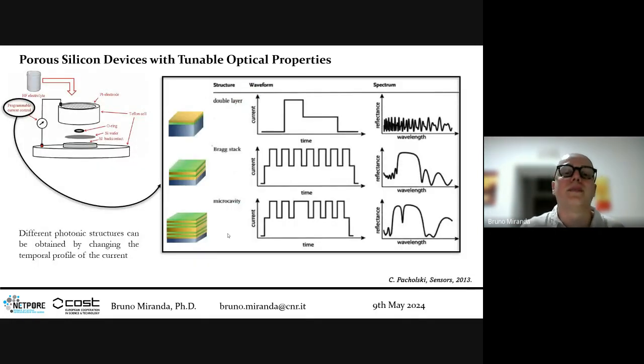How can you do it? Basically, to make a double layer in which you have the convolution of the reflectance of two layers, you apply a high current to obtain the high porosity layer, and then a lower current for the other layer on the bottom. The final result will affect the optical properties. It is important to have programmable current control, so you can tune the current you apply to tune the final properties of your device.